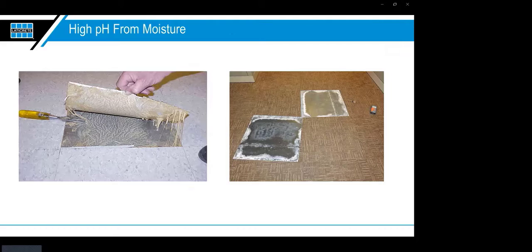Under VCT, resilient flooring, and carpet tile, you can see that high moisture has caused the glue underneath to essentially re-emulsify. Thirty years ago, most adhesives contained asbestos — those black cutback adhesives could handle virtually anything and weren't highly affected by moisture. Today, due to green building practices, we use water-based adhesives. When moisture builds up, it takes that water-based glue and re-emulsifies it back to its bucket state, so it no longer adheres the tile. This is directly caused by moisture from the slab — not a fault of the glue or flooring.